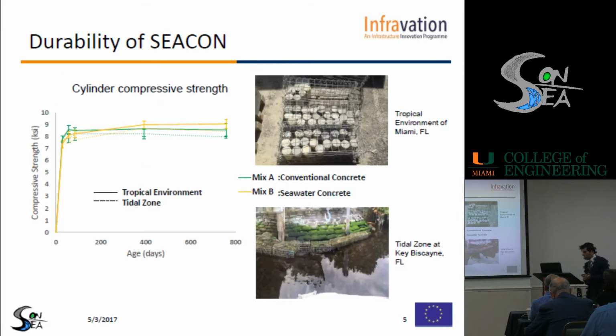So over here, we actually cast some samples 2 years ago, before the official start of our project. We cast samples from mix A, which is a conventional concrete, and then mix B. We exposed them to different environments to make sure that they are durable in both. The first environment is just outside our lab in Miami, Florida, so basically a tropical environment, with the good weather in Miami, right?